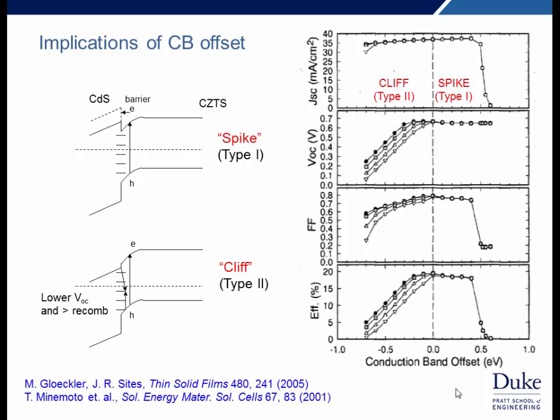One of the reasons for issues with recombination at the interface can have to do with the band alignment at the interface between the absorber and the buffer layer. And for CdS and CZTS, we have two possibilities. Either there can be a barrier, so the electron affinity of the CdS is lower than in CZTS, or it can be the other way around, and we can have a cliff at this interface.